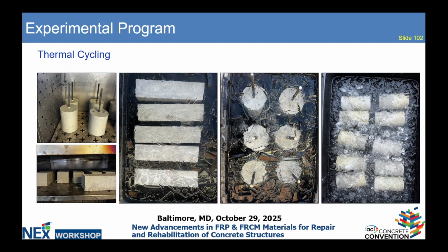So these are some pictures. These are some samples from the oven, and to get 0 degrees Celsius, an ice and water mix remains at 0 degrees Celsius. So we plunged that concrete into the ice water mix directly. We want to call it thermal shock, as we directly plunged the specimens from the oven into the ice water mix, instantaneously, without letting them cool down.